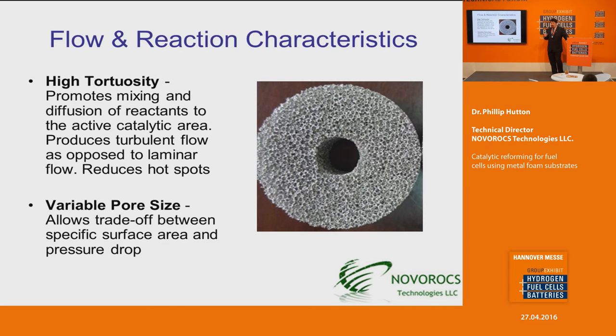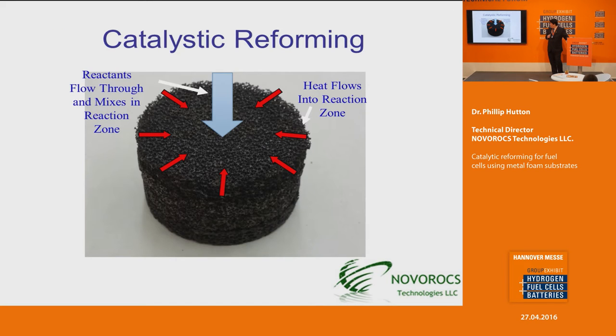Variable pore size. You can vary the pore size. One of the characteristics you want with a catalyst and with any reactor, depending on how your system is designed, is to control the pressure drop across that reactor. If your pressure drop requirements are very tight, you can vary the pore size to reach the pressure drop you want. There is a trade-off in specific surface area, but you do have that flexibility.